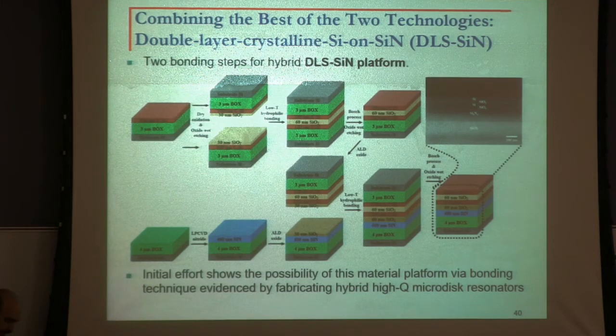The next step is now to start with the silicon nitride, but then adopt the double-layer silicon technology, the first technology that I mentioned, to reduce the power consumption, avoid having p-n junctions. So that requires a 3-layer material, silicon, double-layer silicon, silicon, and then silicon nitride. So this is the chart for the bonding process, where first we do the double-layer silicon as before, and then we grow nitride, and then we bond them together, and we get this 3-layer material.